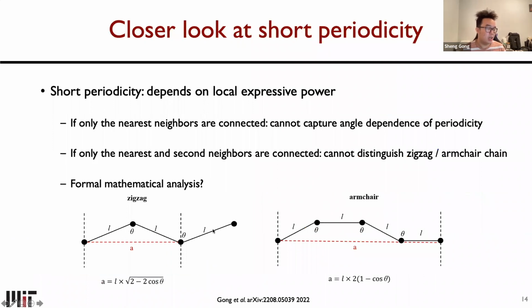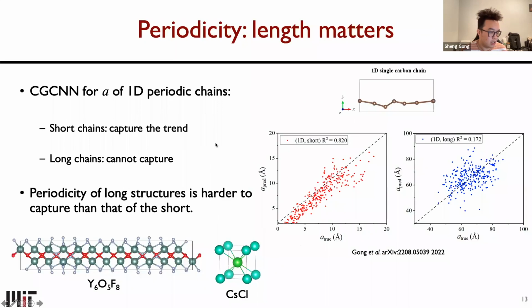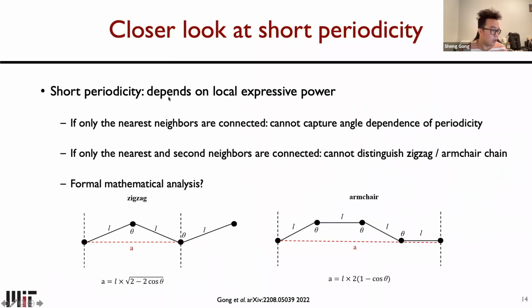And let's have a closer look at short periodicity. Before we showed that the trend of short periodicity can be captured, and we think that how well this short periodicity can be captured depends on the local expressive power of the GNN. To illustrate this point, we come up with two toy models, which are the zigzag one-dimensional chain and the armchair one-dimensional chain. These two chains are patterns of some commonly seen one-dimensional structures in real material science research. And here we also show the dependence of periodicity on the bond length and the bond angle for these two chains.